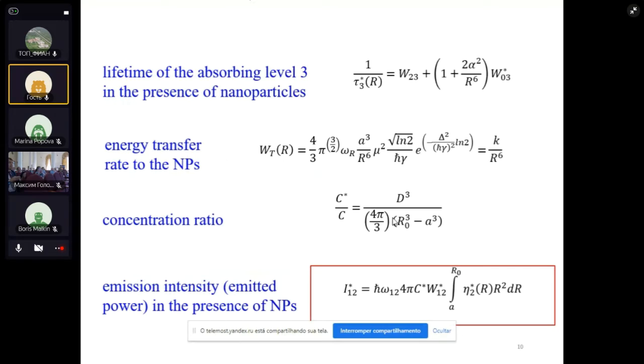Lifetimes are also changed, and energy transfer from the rare earth ion to the metallic nanoparticles, we have shown that we may express in this way. Once again, I will not go into the details, but this delta here is the energy difference between the plasmon peak and the energy of the emitting species. We see that it's a dipole-dipole interaction because the nanoparticles are very big. So distances from the emitting species to the metallic nanoparticles are usually large. So the interaction involving a plasmon and electronic levels of rare earth ions should be dominated by a dipole-dipole interaction. And so we know how to express and treat this.